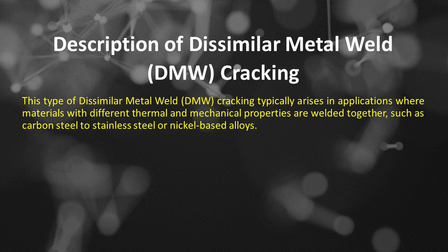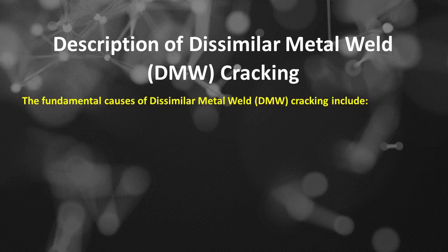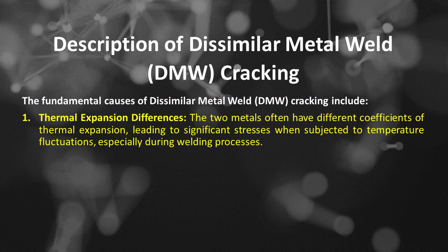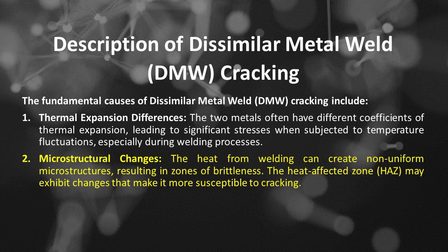This type of dissimilar metal weld, or DMW, cracking typically arises in applications where materials with different thermal and mechanical properties are welded together, such as carbon steel to stainless steel or nickel-based alloys. The fundamental causes of dissimilar metal weld, or DMW, cracking include. Number 1 is thermal expansion differences. The two metals often have different coefficients of thermal expansion, leading to significant stresses when subjected to temperature fluctuations, especially during welding processes.